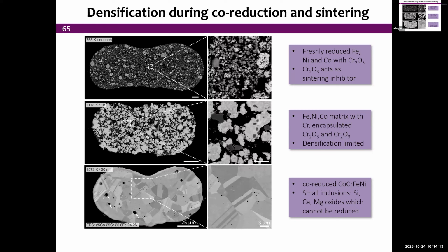So they're actually oxides of calcium, magnesium, and silicon. This is impurities that existed in the original pure iron powder, iron oxide powder, and nickel oxide powders. You buy them at 99.5%, but there's always a little bit of impurities, and those are completely stable. They will not reduce under hydrogen.